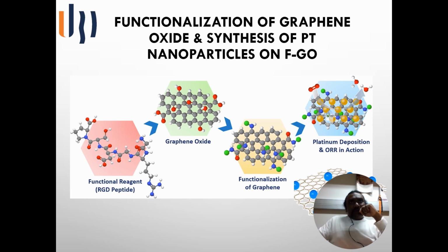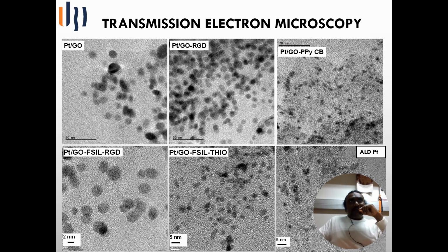We have developed some covalent functionalization methods for graphene, and after this functionalization we deposited platinum nanoparticles to anchor the metal nanoparticles to the graphene sheets. Here are the TEM images of platinum nanoparticles deposited on graphene oxide and RGD functional graphene oxide, graphene oxide and polypyrrole carbon black hybrid material, and multifunctional graphene oxide functionalized with fluorosilane and RGD, and fluorosilane and thio groups. The final one is platinum deposition on graphene monolayer using the atomic layer deposition method. In more or less all these images, the platinum nanoparticle size is around 4 nanometers,